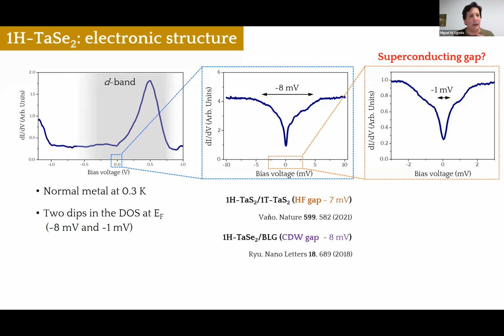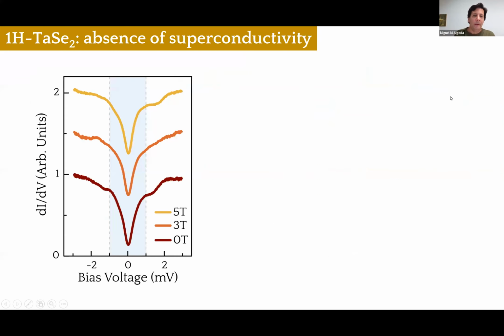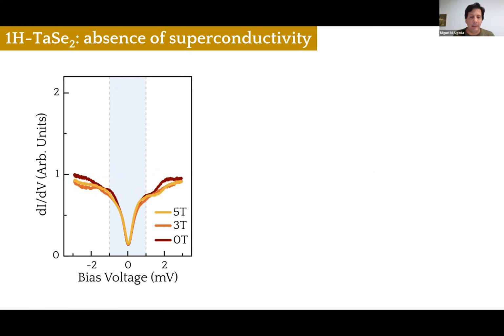So whether this material is superconducting or not at 300 millikelvin is something that we looked at in the past, right? Okay, so here I show you 3 different curves taken with the same tip and the same location on the sample, at 0 Tesla, at 3 Tesla, and at 5 Tesla. And as you can see, they basically lie on top of each other, or are identical, and therefore we can rule out that this peak is related to superconductivity.